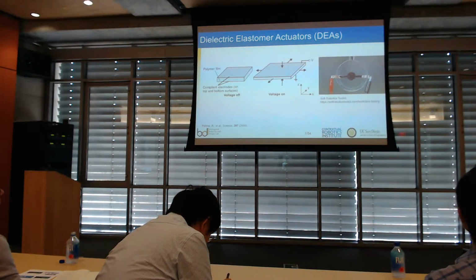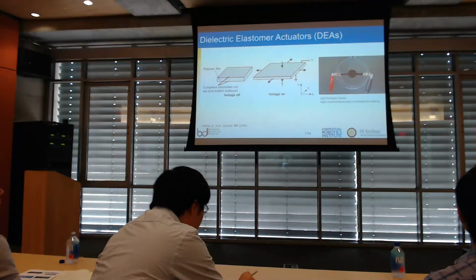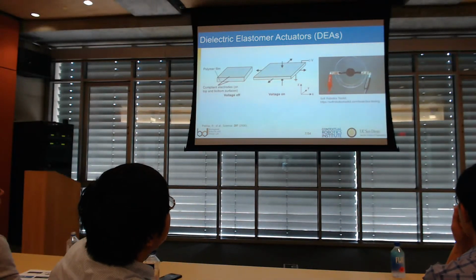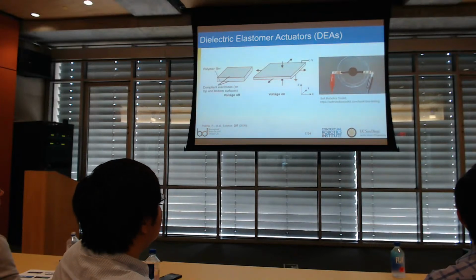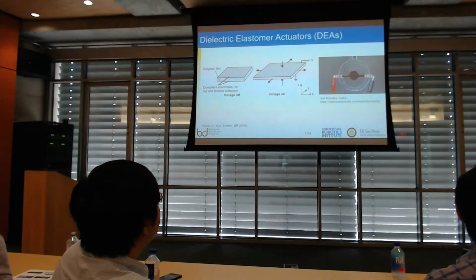And here's a video of one of them working. So the transparent section around the outside, so there's a rigid ring on the outside, and then there's a transparent film, and then the black part is where the electrodes are. So then they're applying a voltage of maybe 5,000 to 7,000 volts to get this actuator to move.